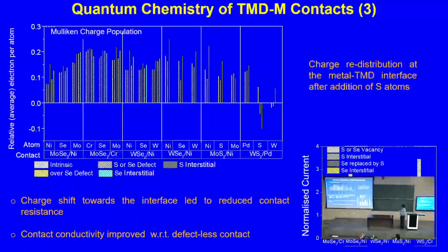We tried many combinations, as I said, and we found those possibilities which give you the best conduction possible and also selectivity between having either a donor state or an acceptor state. Now if you have to make an n-type contact, you have to populate more electrons in the conduction band, for which you need donor states. If you have to make a p-type contact, you have to populate more holes in the valence band, for which you need acceptor states. And now we found a way by which you can selectively create either donor states or acceptor states. The catch here was that not only the defect, but you also need a particular metal. So it's a hybridized state of the defected site, a certain vacancy or a certain interstitial being introduced, and a metal on top of that. We call that metal induced gap states.